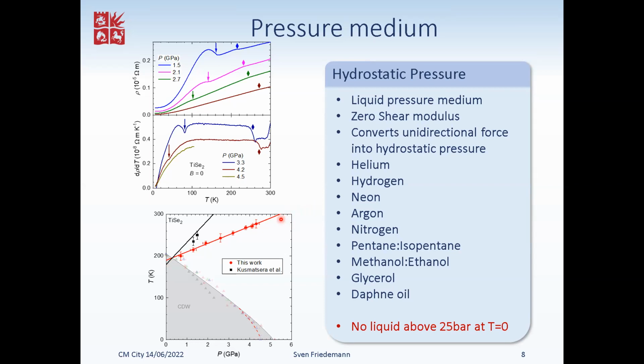Question, please. Isn't it when glycerol solidifies, it becomes glassy? So is that a worry that it's glassy? Never, actually. Glassy sounds good because it keeps the shear modulus low, but nevertheless it has a shear modulus even when it's glassy. So in the sense of a pressure medium, it is not really bad, but it already disqualifies itself as a liquid. It's not a liquid anymore. Even glasses have a shear modulus. So glassy, but glassy is better than not. Crystalline is certainly worse because then you've got a tensor, and you can have quite some more pronounced effects. Yes.